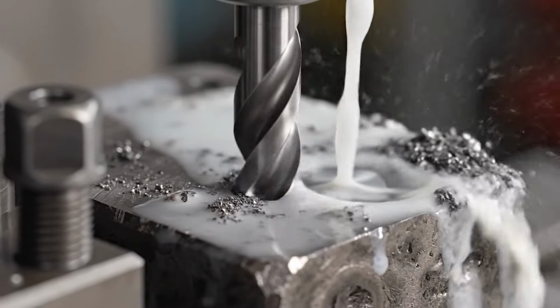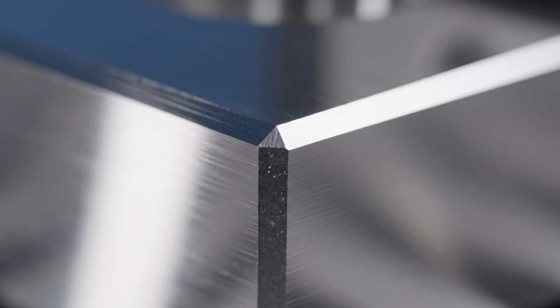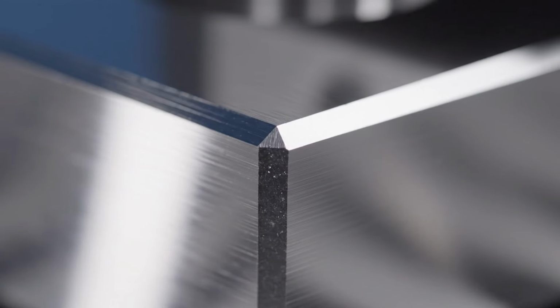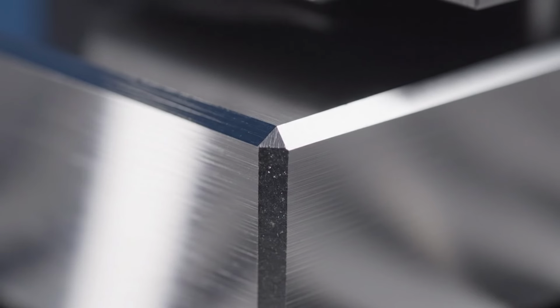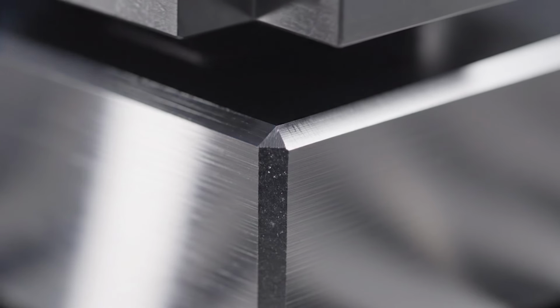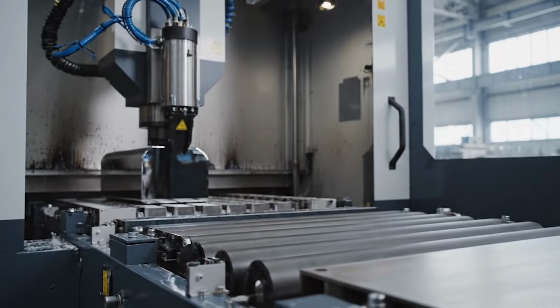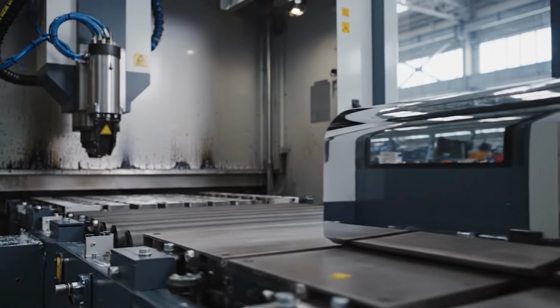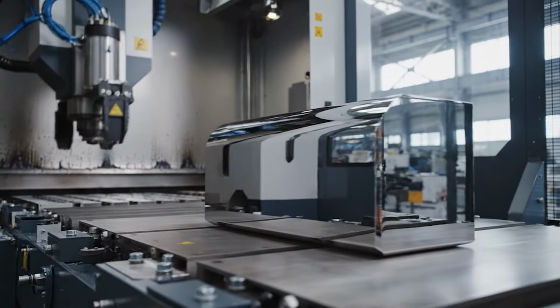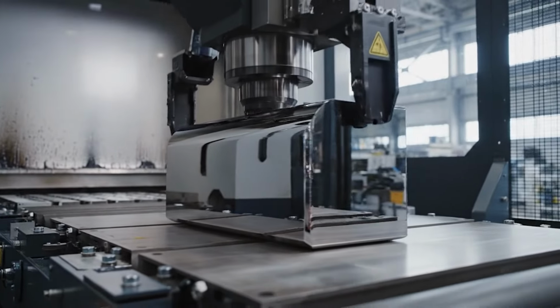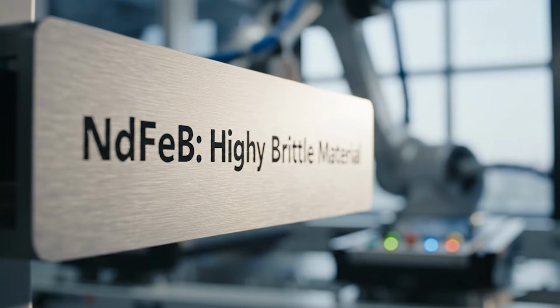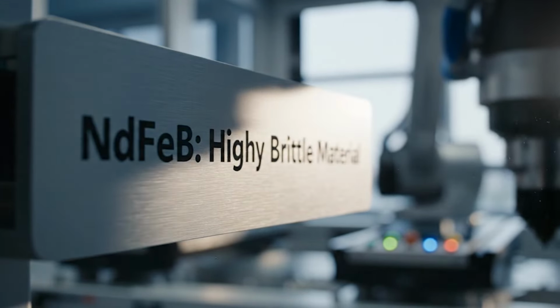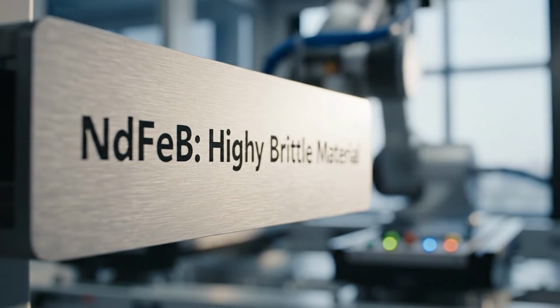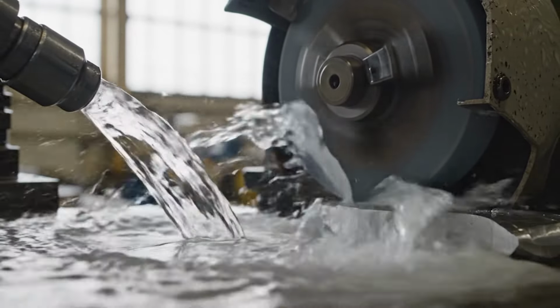For hours, the compacts are held under vacuum at this extreme heat. Slowly, they shrink by nearly 20%. Their density increases. Internal grain boundaries form. What emerges is no longer a fragile chalk block. It is a solid, dense magnet core with the strength to survive machining. The sintering process determines coercivity, energy product, and overall performance. A single mistake in temperature or timing could compromise the entire batch. Precision is everything.